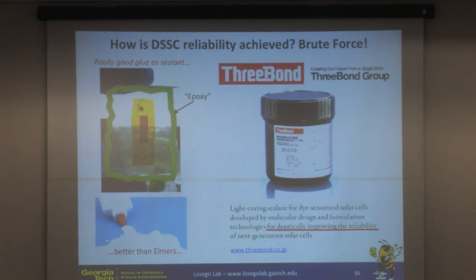And the way they've gotten to reliable performance is not really an eloquent way. Rather, it's through brute force. It's really just using very good sealants on the exterior of these devices. So take your device and then encapsulate it with a really good glue, a really good epoxy. Okay, so it's better than Elmer's. There's in fact an entire industry surrounding the design of these epoxies to encapsulate these dye-sensitized types of devices. The other trick here, of course, is that the electrolyte they're using is non-aqueous, right? So non-aqueous electrolyte, and then seal it to prevent any ambient water from getting in.